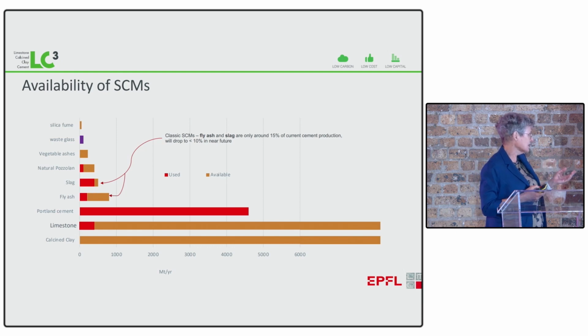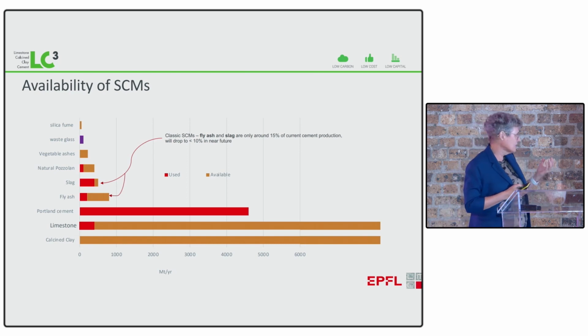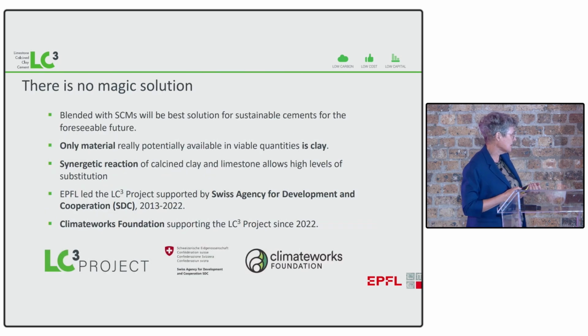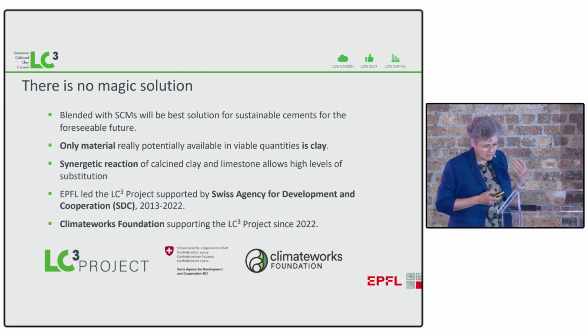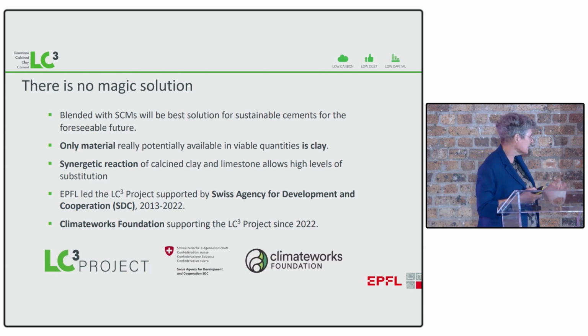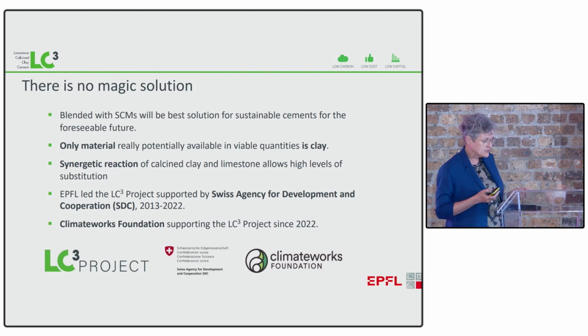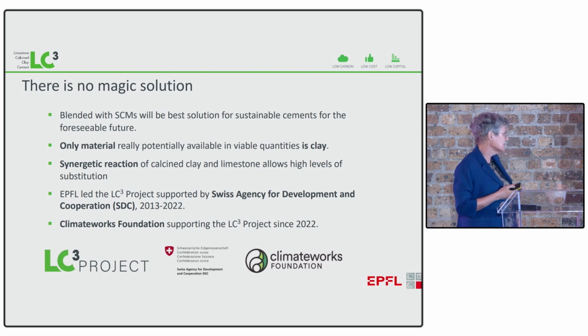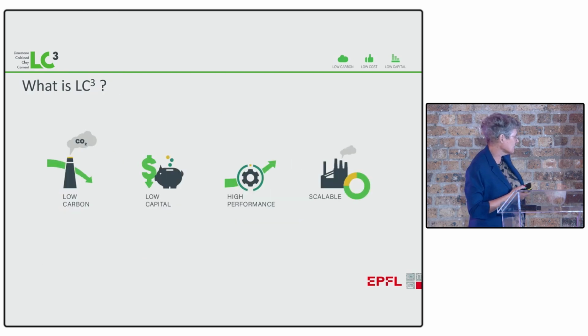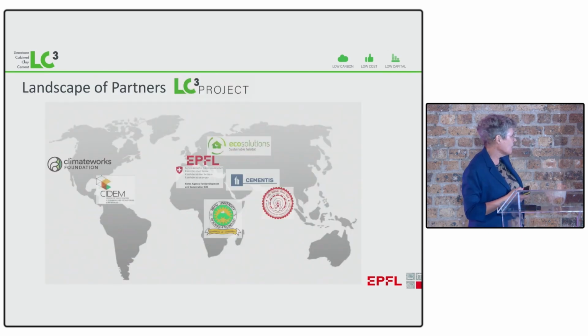And this is where calcined clay comes in, because it's really the only thing that's available in the enormous quantities we really need to make a difference. And this led us to what we call the LC3 project, where we realized not only were these calcined clays, these clays that you can calcine, massively abundant, but we could get a synergistic reaction with limestone. Limestone's also super abundant, often at the cement plant, and we could then go to very high levels of substitution. So what is LC3? LC3 is this family of materials.